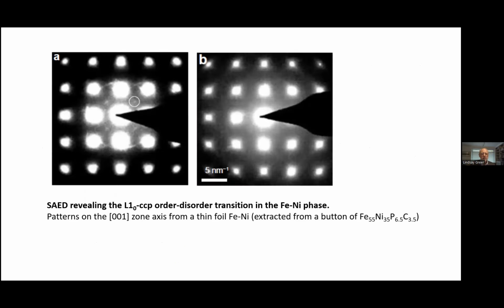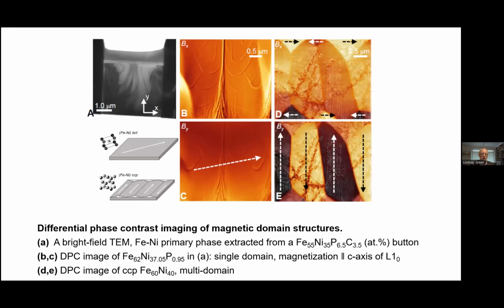The most unambiguous evidence for having the tetrataenite phase we're looking for is these so-called forbidden reflections. They shouldn't be there, but we are getting reflections. It's a sign of the phase being not cubic and having some ordering in it. Magnetic properties we have not measured in a way that people who make magnets would be in sympathy with, but you can detect in the electron microscope whether magnetic domains are small and compensating each other in direction, or more like a single domain, which is what you might expect for a permanent magnet material. So again, there's a suggestion that in these middle images for our tetrataenite sample, we have something that has desirable magnetic properties.